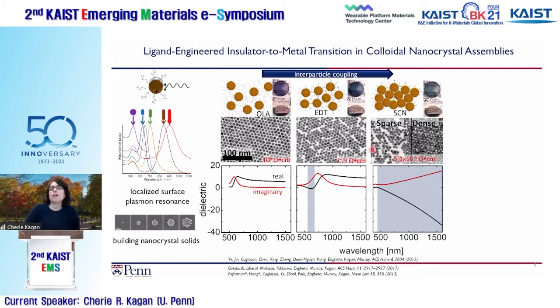And so you can see this on the left-hand side in a monolayer. You can see that the volume where there are no nanoparticles, of course, is getting bigger because the system's contracting. But if you were to make a dense film like we use for electrical or optical measurements, it would look something like the one here on the right, which looks like a metal film, but with lots of empty spaces. And so sometimes we refer to this as a diluted metal, right? There are fewer metal atoms to contribute electrons to the electrical and optical properties.